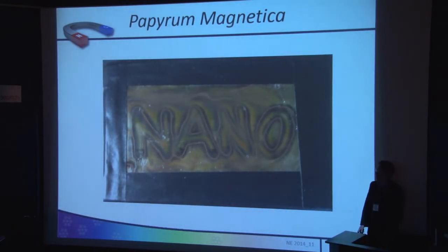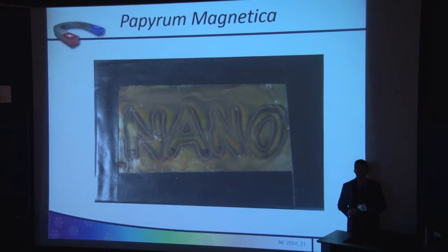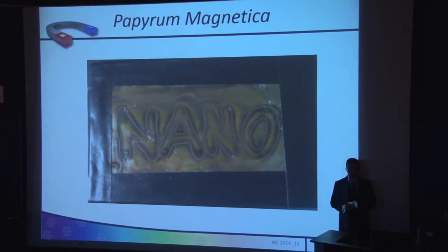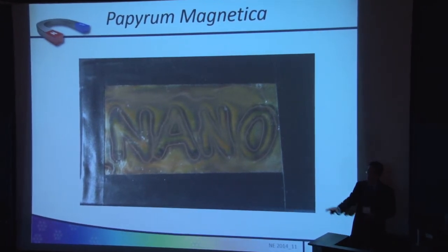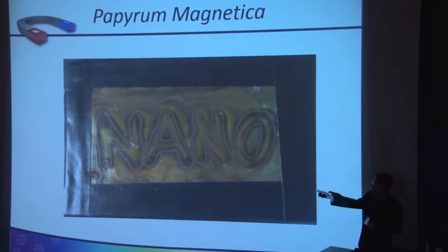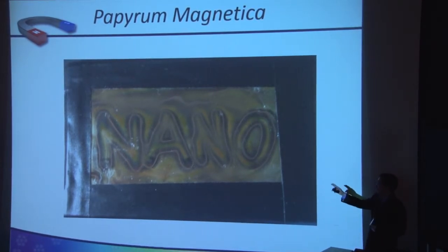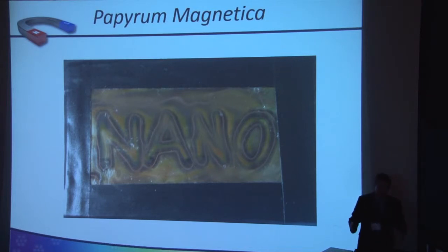This is the second prototype that we just constructed yesterday. Instead of the Alnico bars, we use a ceramic magnet, which is a continuous sheet. So the overall thickness of this prototype is much thinner, and as a result, we need a much weaker magnetic field in order to actually magnetize the hysteresis layer and obtain the photonic crystals we need. So as you can see, we can still obtain multiple colors, and the writing is much more accurate since we can use smaller magnets with weaker magnetic fields.